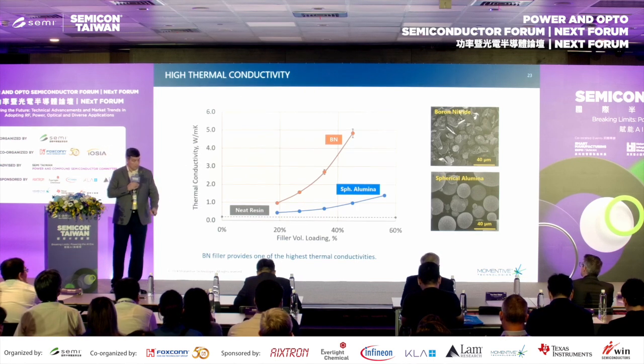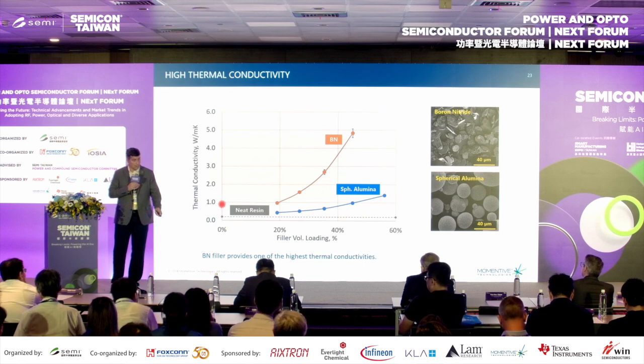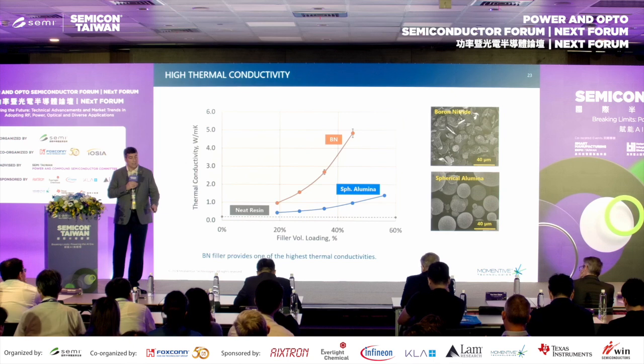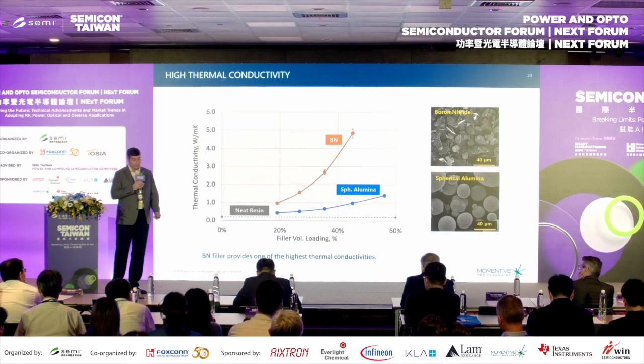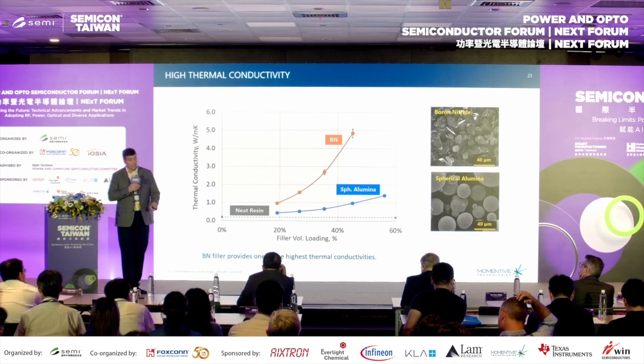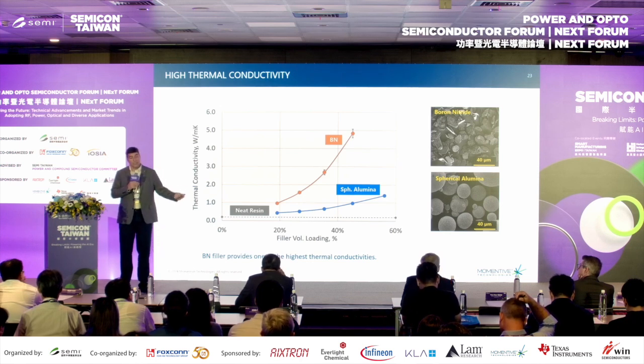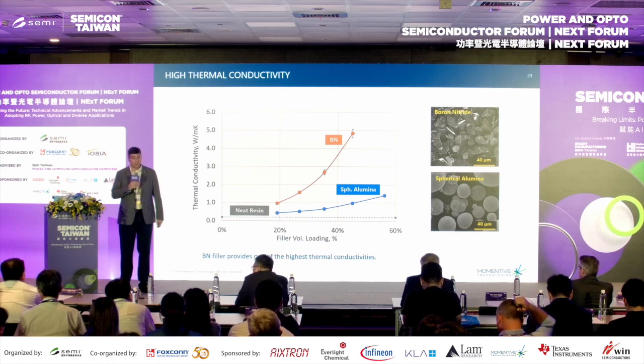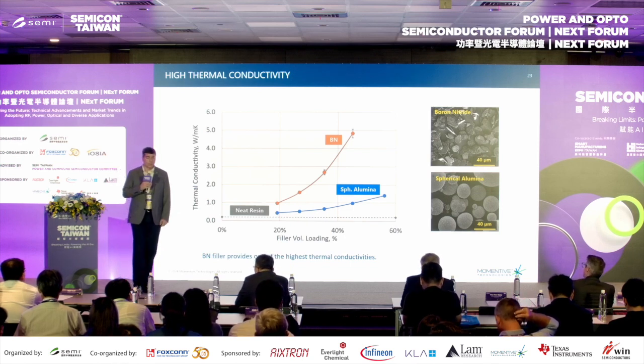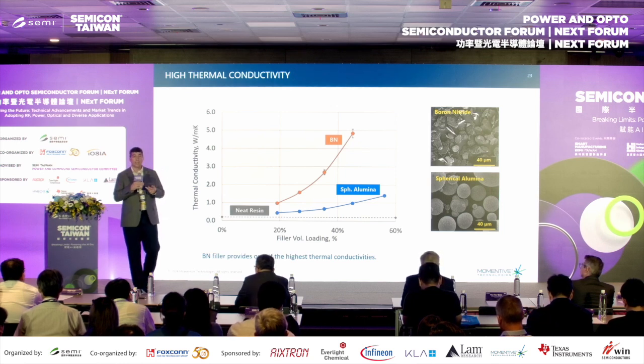So on the bottom here, check this out. We've got our neat resin down here along the bottom. As you add your spherical alumina up to 40, 50, 55 volume percent, you get up to about 1.5 watts per meter Kelvin. With the BN, you surpass that at, what is it, about 25 volume percent, right? And it just continues to go up from there. Like I said, it's also much less abrasive to the system. There's also potential to combine these, right? So you get the best attributes of both.